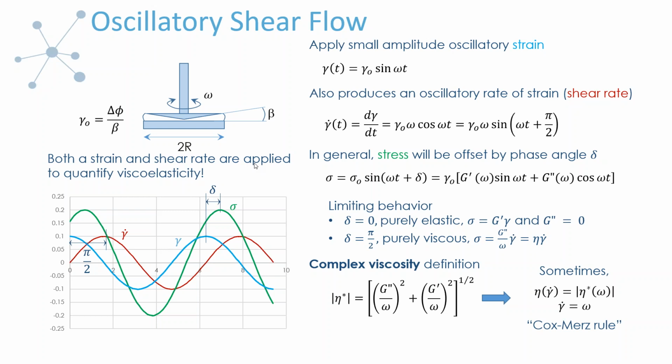So I think that the best place to apply this rule, and where I've used it, is lower to moderate rates and frequencies, because you have experimental challenges with high frequencies, and then also you would expect deviations from an equilibrium state that comes from the steady shear that's not really there in the oscillatory measurement. But it's certainly something that you can try out and see how it works. If you have the ability to do these experiments, you can see over what range they overlap and agree.